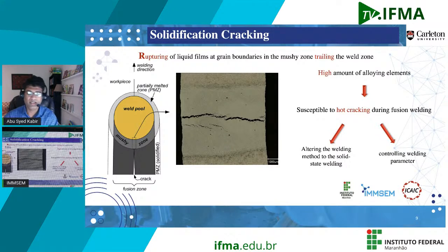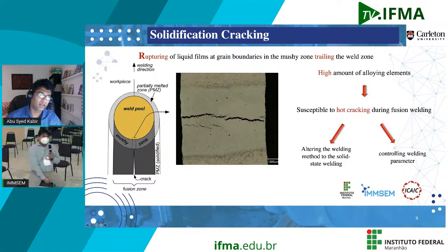So when the weld head, or let's say the arc, moves, the melt pool moves in the welding direction, it leaves a mush region, which is a mixture of the solid and liquid, like a two-phase region. And within this mush region, some of the phases get solidified, so it's solid, and some of the phases still remain as liquid.